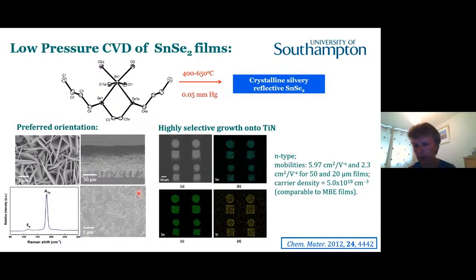we did, well, we published in 2012, and this was work that Chitra did when she was in her fellowship from the Royal Society working in Southampton. This is a tin chloride complex with this diselenoether. It's a very simple distorted octahedral molecule. It's neutral, it's an oil, it has some volatility, and in a low pressure CVD experiment, we can deposit SnSe2, so tin diselenide, in a very nice manner with control over the orientation of the crystals, depending on whether we have thicker or thinner samples. And we can do that by controlling the quantity of the precursor.